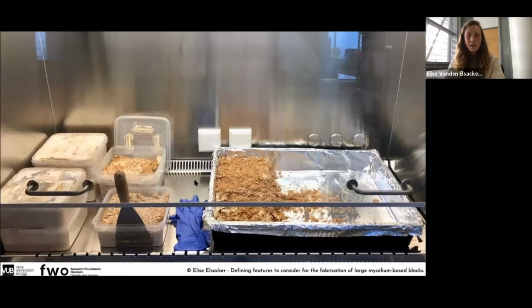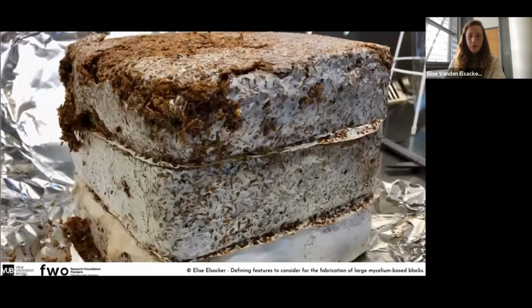Here the samples that were grown directly in the boxes and then placed next to each other didn't really achieve a seamless connection between the blocks, and that was actually a challenge along the whole research: to have this seamless connection. The second test was performed by first cold pressing all those living blocks before stacking them. The goal here was, like I said before, to enhance the mechanical properties by having a larger densification.